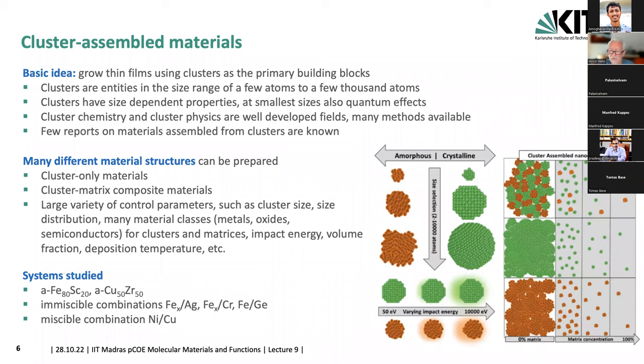Of course, if you have a material like the one shown over here, you can also change the volume fraction, the ratio between matrix and cluster material, irrespective of the thermodynamic phase diagram, at least in the preparation technique. And then you have to study, of course, whether this is stable or not. One further parameter could also be the deposition temperature. But typically, we have chosen the deposition temperature of the substrate to be very low, so we do not have thermal motion of the clusters to move them around, and they stay wherever they land.